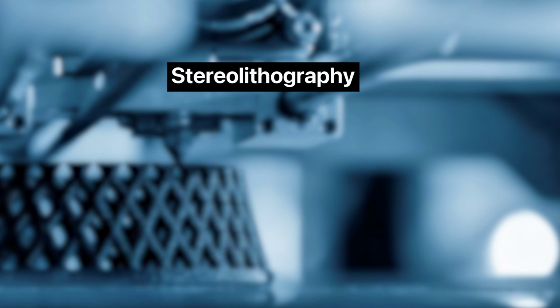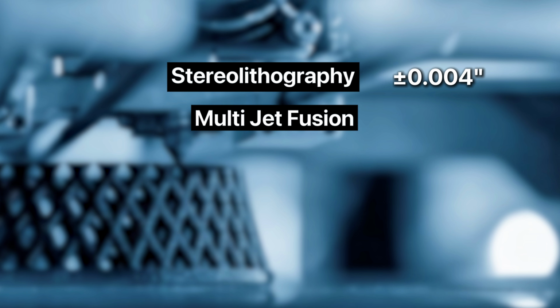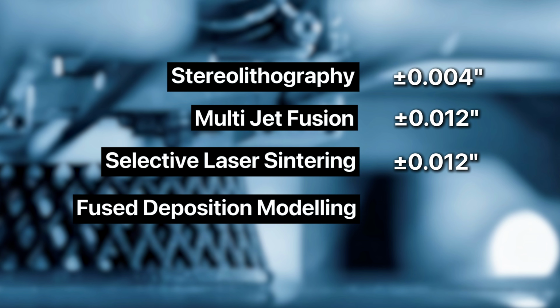In terms of precision, SLA ranks at the top and can achieve a tolerance of ±0.004 of an inch or 0.1 millimeters, followed by MJF and SLS, with FDM being the least precise at around ±0.020 of an inch or 0.5 millimeter. However, FDM is the most cost effective in terms of making prototypes and large parts. So you ultimately have to pick and choose which method to use based on your design needs.